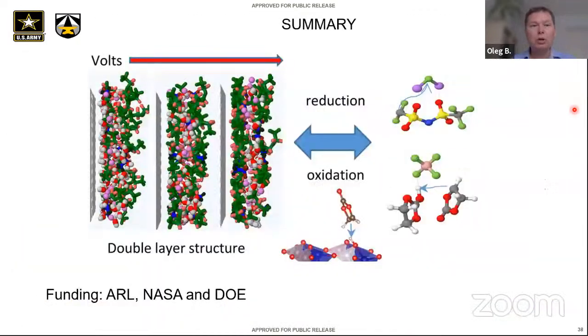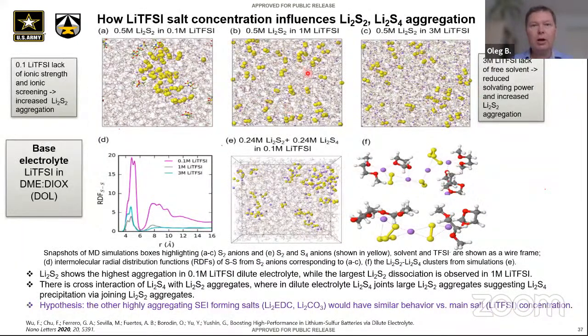So what I'm going to do is take 3 salt concentrations: 0.1 mole, 1 mole, and 3 mole of lithium TFSI, using the same DME dioxolane mixed solvent, and look at how the concentration of that main salt affects aggregation of this other salt, like Li2S2, Li2S4, in this case Li2S2. And what I found was somewhat surprising. At 1 molar, there was the least aggregation. There were local aggregates, but it wasn't phase separated.